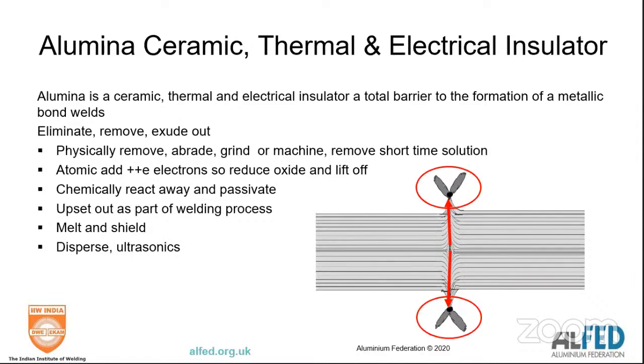You can atomically remove it. You can use electricity, electron flow, by adding a couple of electrons to reduce the oxide and lift it off. You can chemically remove it and passivate the surface. You can upset the alumina out as part of the welding process, a forge weld, and you can melt and shield it with laser welding, with very high temperature methods. You can melt that alumina and remove it. Remember that it's heavier than aluminium, so it'll sink if you're not doing it. And you can disperse alumina through processes like ultrasonics.